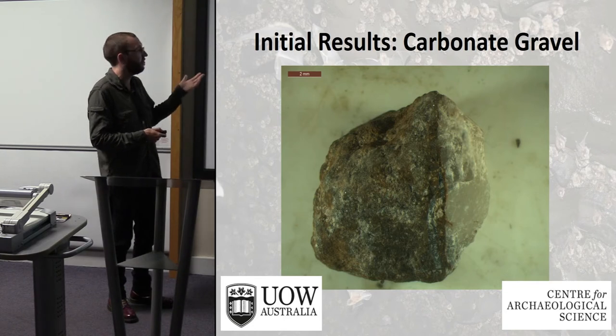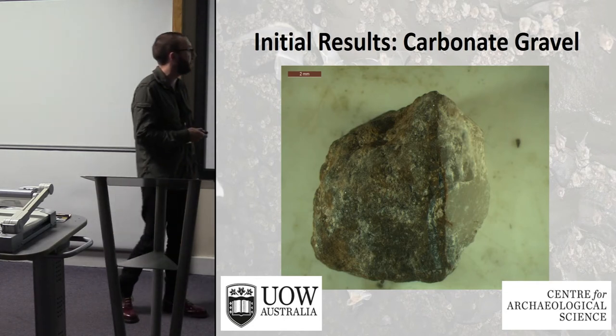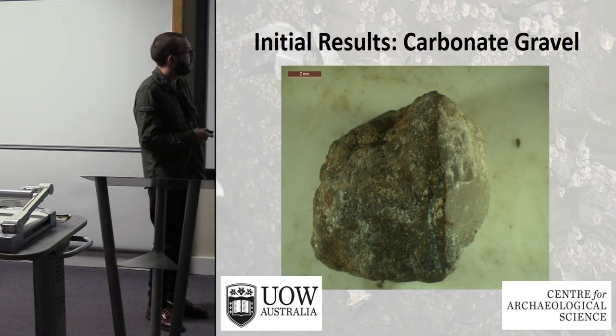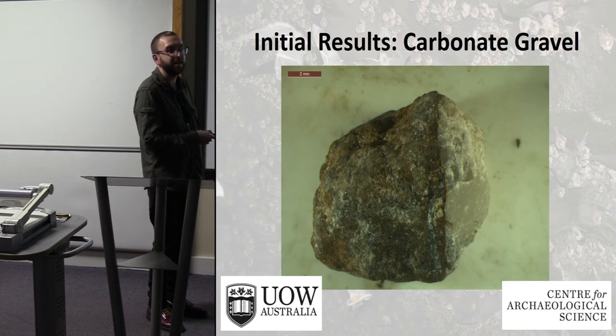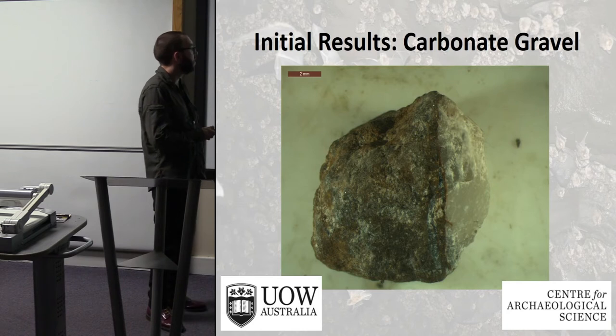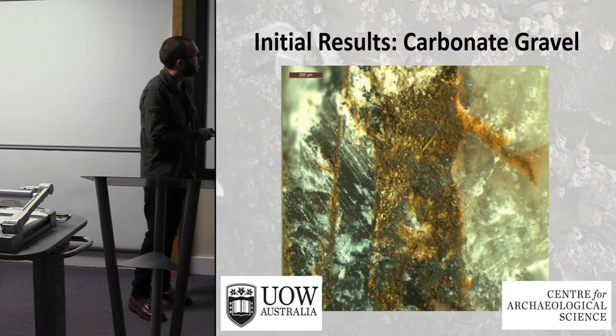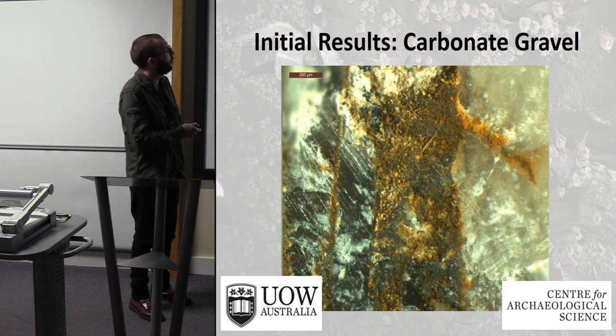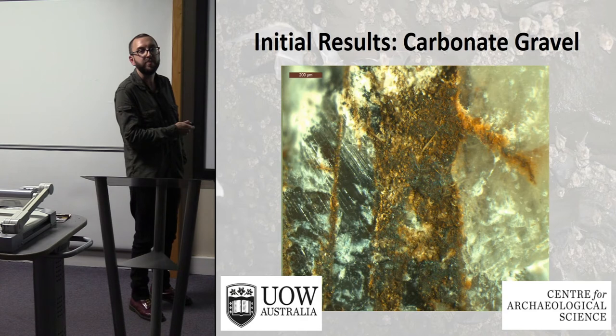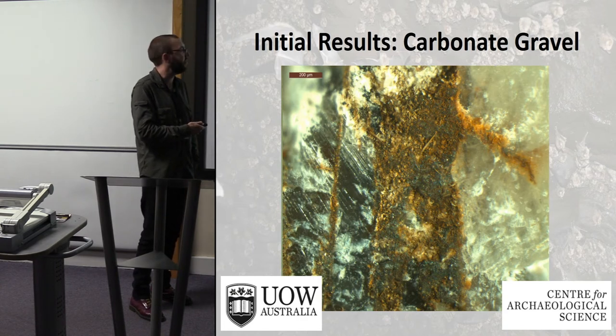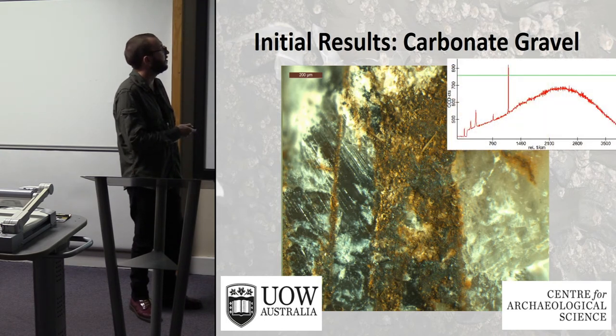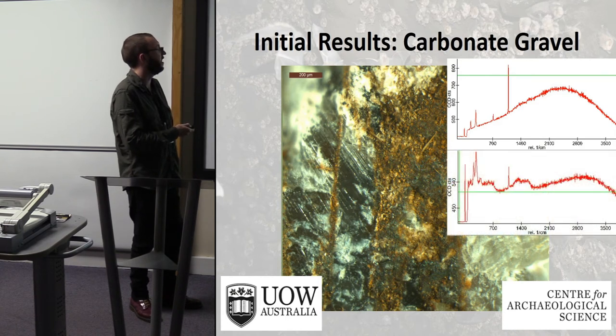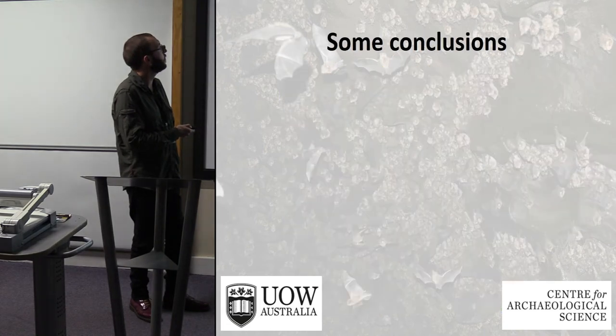As well as bone, this is a piece of carbonate gravel — just a piece of white limestone when it went in. After three months, there's a clear line from where it was buried in sand and the upper section which was sticking into the guano. You can see sand welded into oxides that have been precipitated onto it. Raman spectroscopy shows carbonates and hematite from that welded area — I was quite surprised that progressed that quickly.